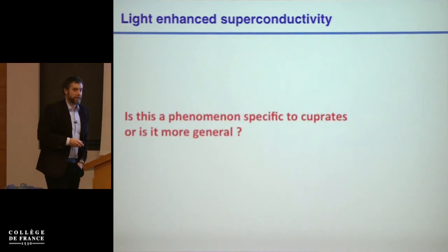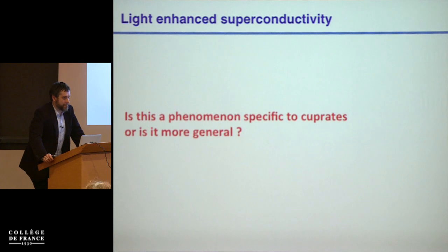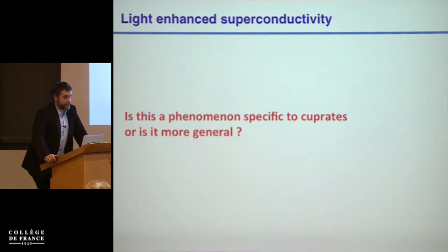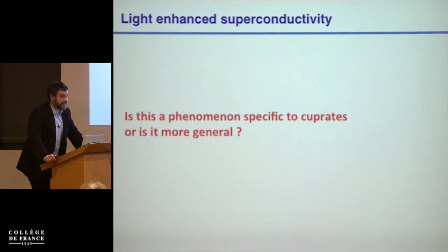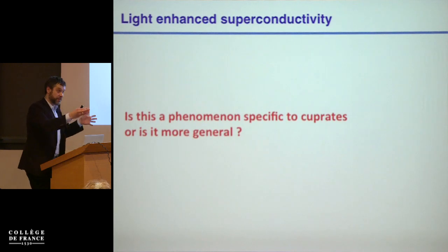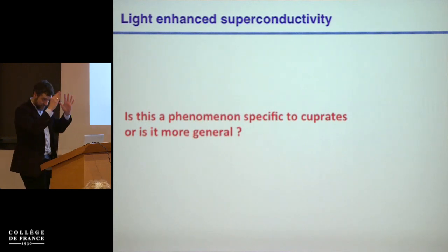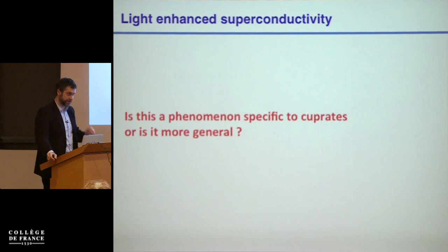Yes, please. Is there anything you could do to probe magnetic correlations within the plane? I mean, of course, one could probe static magnetic correlations in the way that I told you by scattering, by resonant soft X-ray diffraction. But you are thinking about something different, aren't you? No. So the answer is I can do resonant X-ray diffraction and measure, provided that they're reasonably long range, so 2, 3, 4, 5 unit cells, and they form a peak. In principle, I could measure those.